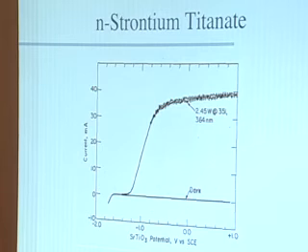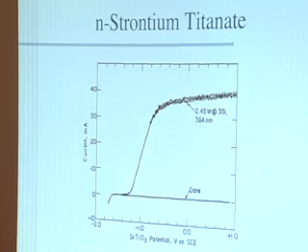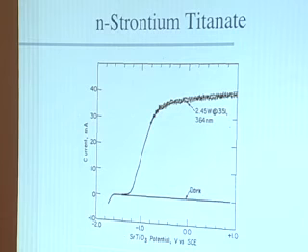I shine light on it, and now I have holes down here. And so as long as there's enough band bending to do the electron hole separation, those holes come out, and I oxidize water. So I'm hitting this now with about 2.5 watts of UV light in about a 1 millimeter squared area. So that's on the order of 300 plus suns intensity that I'm hitting this semiconductor with, and it's very happy under these conditions, believe it or not, and it's generating, you can see here, on the order of 35 milliamps per square millimeter.